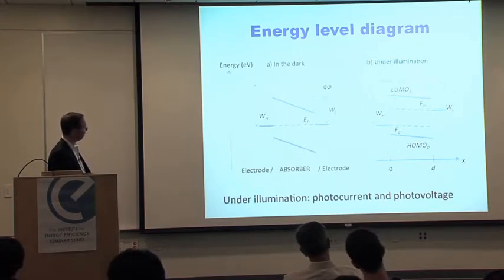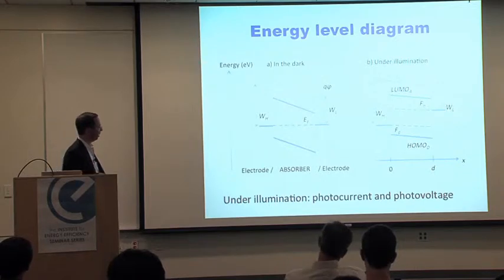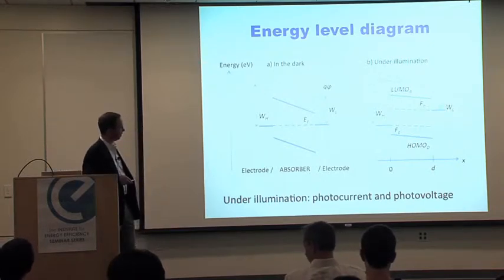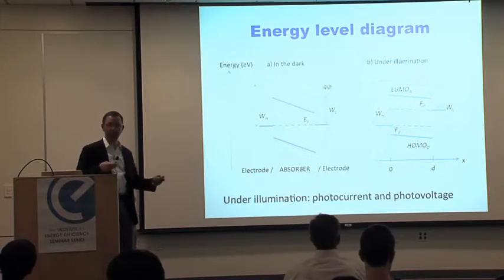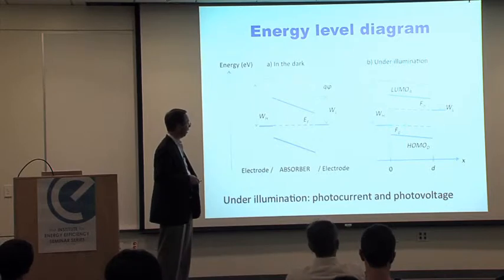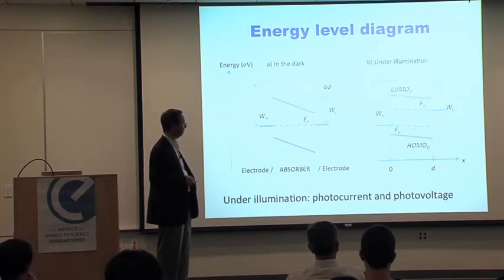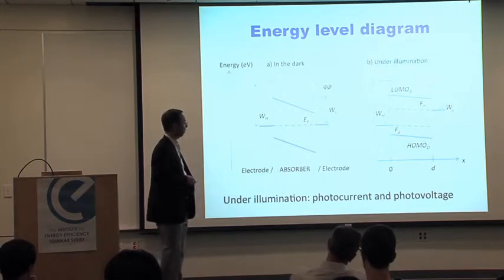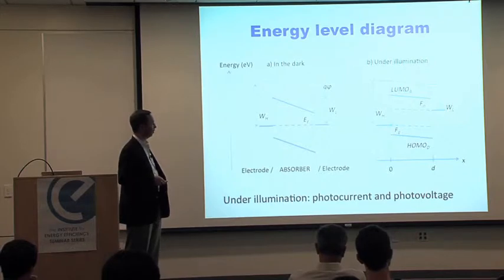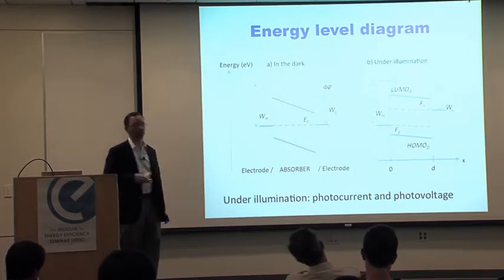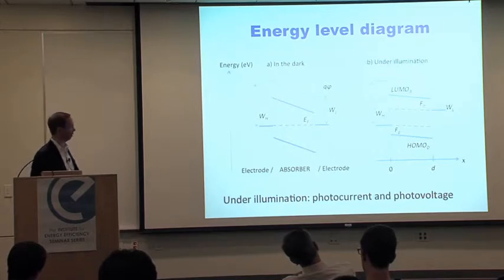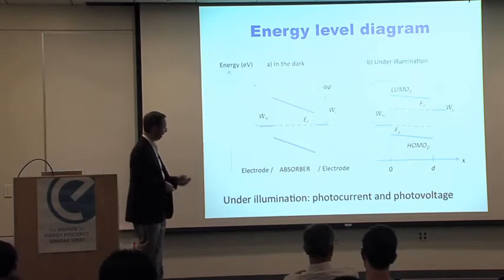But this is the energy level diagram in the dark at equilibrium, where you line up the work function of the metals with the Fermi level for your absorber. And on the right-hand side here is a schematic of what happens when the solar cell is operating, where you're now creating holes and electrons in the device, you have spatially separated the holes and the electrons, and their density is described by these quasi-Fermi energies, which is the electrochemical potential for holes and electrons. You get a photovoltage, which is the difference between these quasi-Fermi levels at the two electrodes, and you get a current, which is described by the gradient of the quasi-Fermi levels, or the gradient of the electrochemical potential.